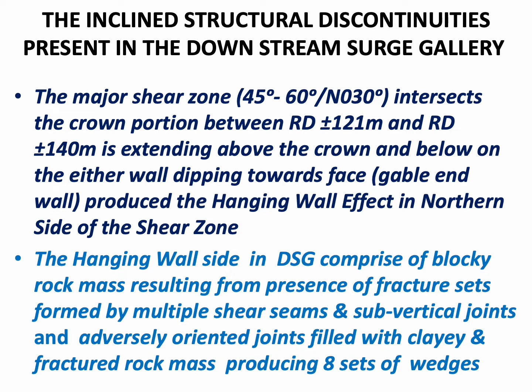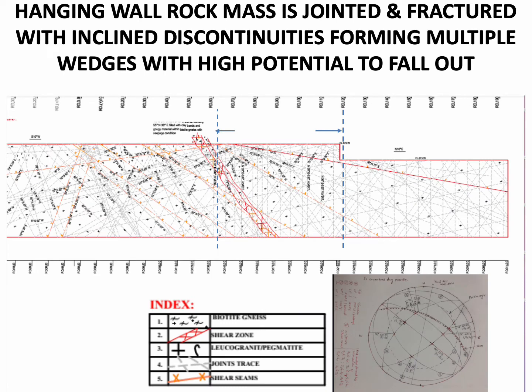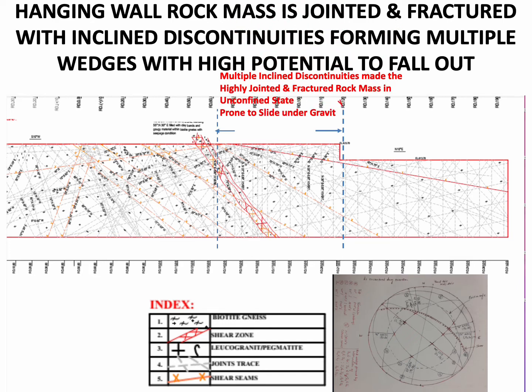The hanging wall side in downstream surge gallery comprises blocky rock mass resulting from presence of fracture sets formed by multiple shear seams and subvertical joints and adversely oriented joints filled with clay and fractured rock mass, producing 8 sets of wedges. So, talking of the inclined discontinuities, hanging wall rock mass is jointed, fractured with inclined discontinuities forming multiple wedges with high potential of fallout that we have already discussed in the stereo net as well as on this. So there are multiple inclined discontinuities which make the highly jointed and fractured rock mass in the unconfined state prone to slide under gravity. So from the prerequisites that were required, we saw that the multiple inclined discontinuities are making the highly jointed and fractured rock mass in the unconfined state becoming prone to slide under gravity.